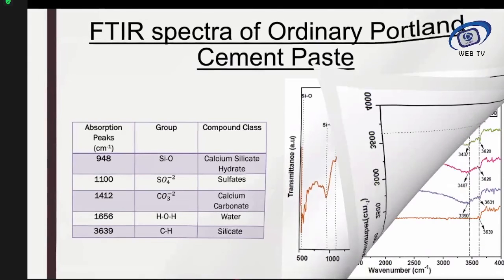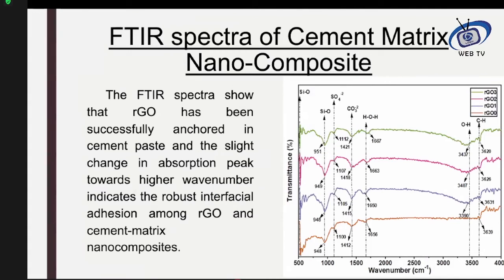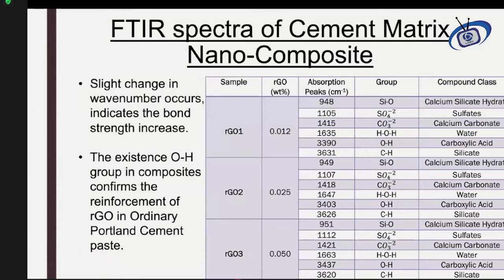Now, this represents the FTIR spectra of all the samples used with the different ratios of the RGO. Summing up all these peaks shows that there is a proper inclusion of reduced graphene oxide into the cement. The peaks of the cement and the peaks of the reduced graphene oxide were present in this spectra, representing the successful inclusion of the different percentages of the samples.